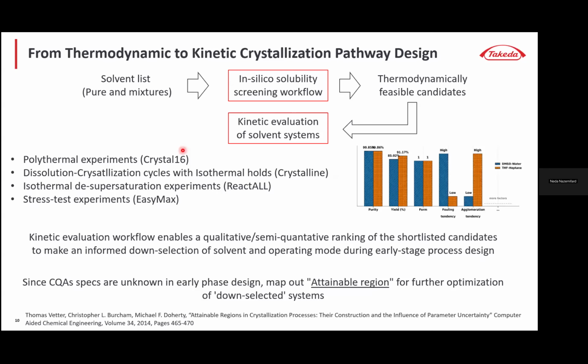So polythermal experiments like cooling curves, for example using a Crystal16 unit to see the crystallization and dissolution points, and isothermal hold experiments using something like a Crystalline setup to monitor how crystals nucleate or grow at constant supersaturation. Desupersaturation tests to look at nucleation and growth rate, and even stress testing in small reactors like EasyMax to see how robust a system is under different conditions. By doing this, we qualitatively or semi-quantitatively rank the candidates from a kinetic perspective.